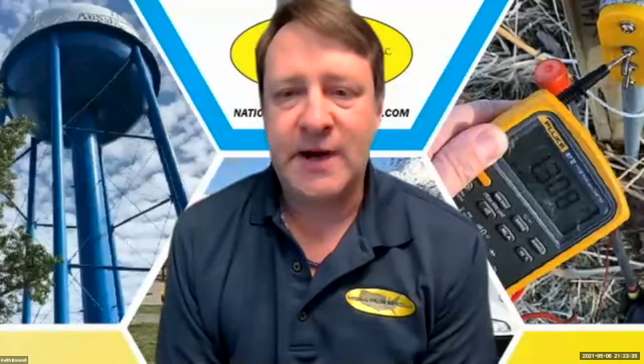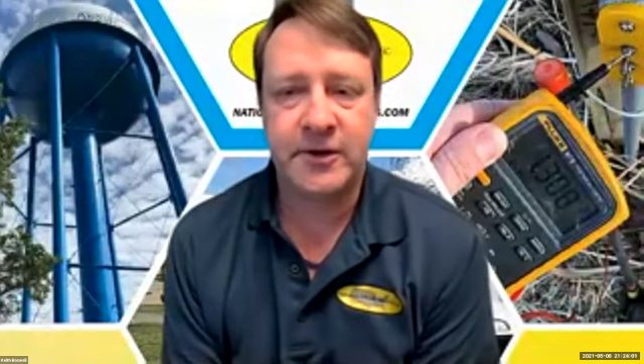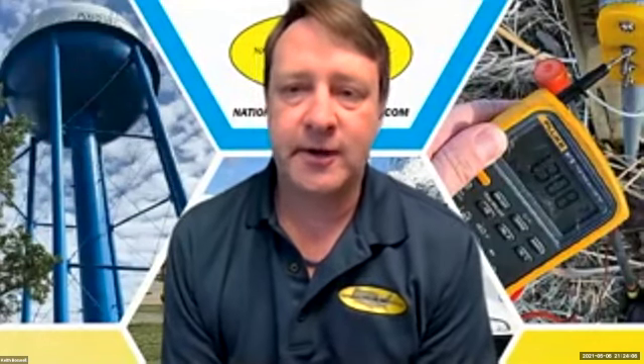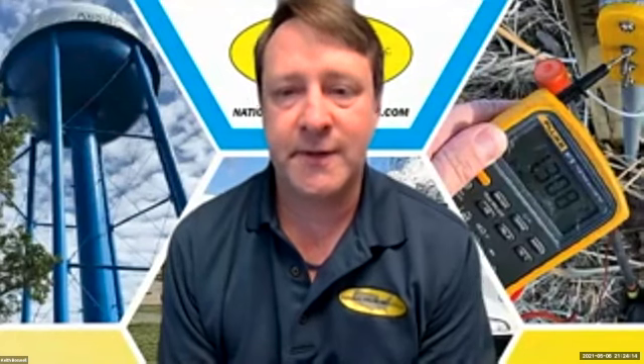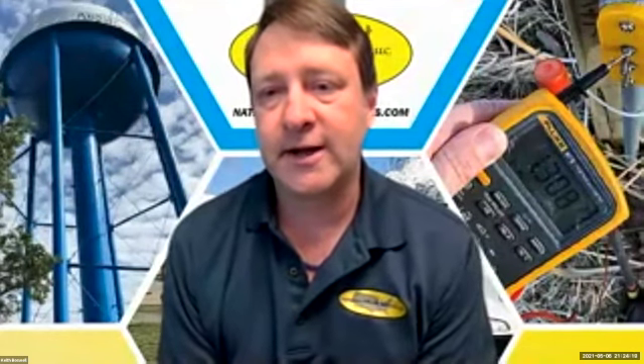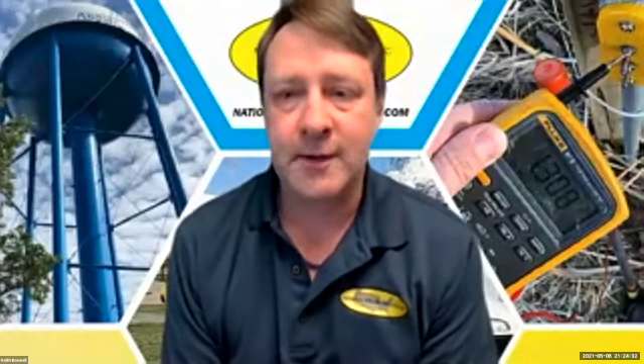Yeah, absolutely. The inline inspection is just another tool to help corroborate whether you're adequately cathodically protected or not. If they perform an inline inspection and determine that they have metal loss, and if it's external, and they have some regulated period of doing those ILI inspections, they can see if there is active corrosion from year to year. Are they seeing more metal loss from survey to survey? That would lead you to the conclusion that maybe the cathodic protection is not working effectively, where there's corrosion still occurring on that pipe. So it's definitely a tool to use in conjunction with the cathodic protection surveys and testing. A lot of times operators will overlay both sets of data to see if there's any correlation between the two. Gotcha.